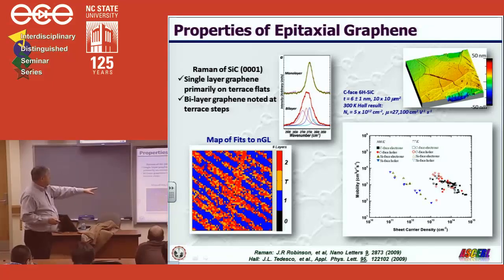Over here on the right, these are some of the best values we've achieved under an argon-based process. But it's still the same message that I showed you earlier: the silicon-face material always has less mobility than the carbon face.